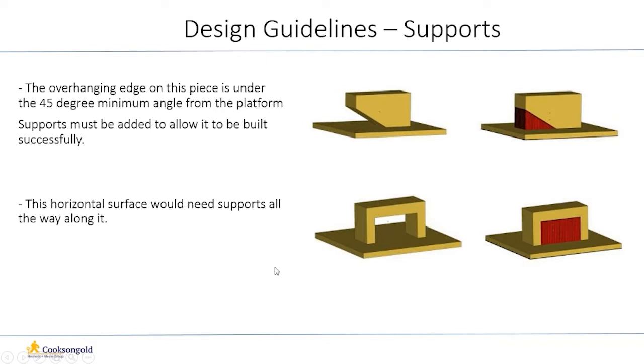On the illustrations, you can see the part, and the red areas are the supports that would be required. The overhanging edge on this piece is under the 45-degree minimum angle from the platform, so supports must be added to allow it to be built successfully. If supports aren't added, that can mean the part can burn or collapse in on itself. So the supports are needed to hold it up. The horizontal surface on the bottom part would need supports all the way along it to be successful.